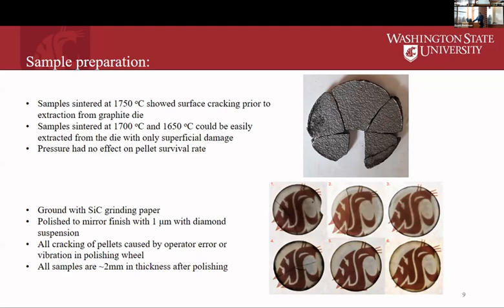After we extracted our pellets, we ground them with silicon carbide paper to remove any surface graphite left over from the sintering process, and then polished them with diamond polish to a mirror finish.